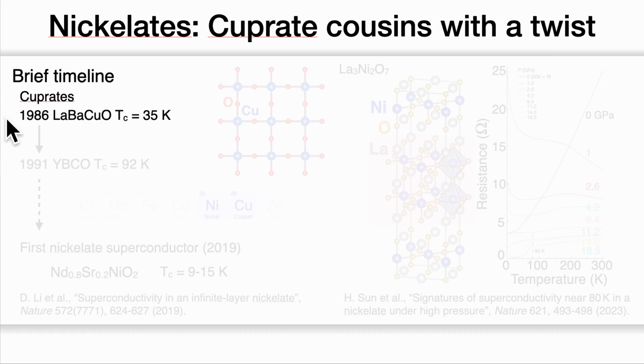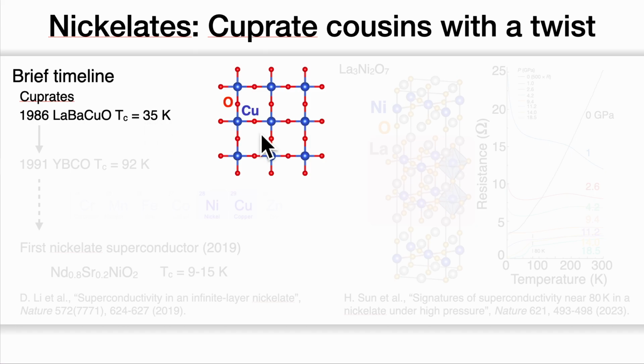Here we go through the brief timeline quickly. In 1986, LBCO revealed a superconducting transition temperature, Tc, around 35 Kelvin, which is quite high compared to conventional superconductors. And the high Tc is believed to be due to the electrons pairing in copper-oxygen planes. In 1991, YBCO was discovered to have a Tc around 92 Kelvin, which is higher than the boiling point of liquid nitrogen at 77 Kelvin, entering the high-temperature superconductor region.